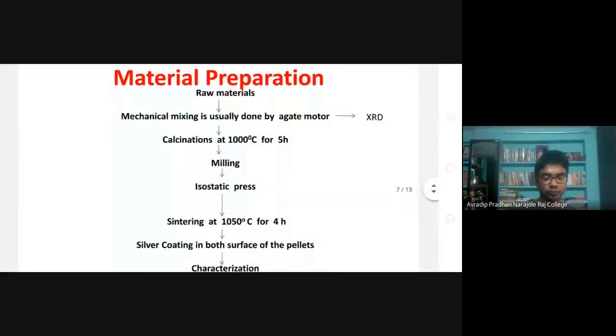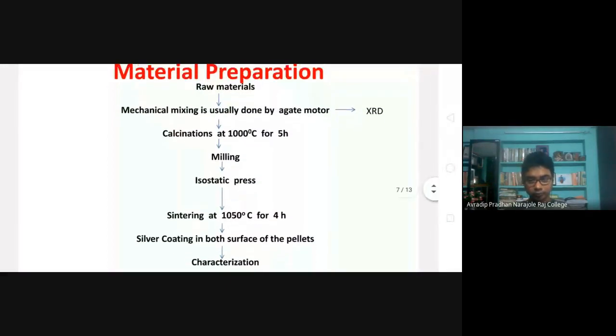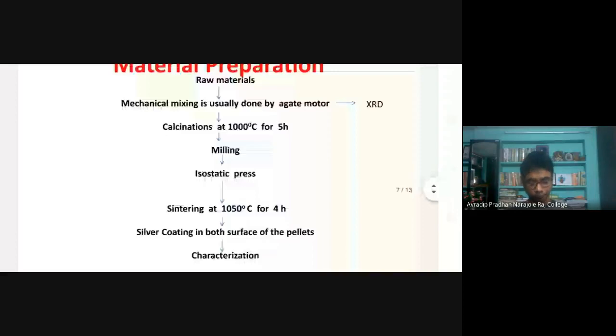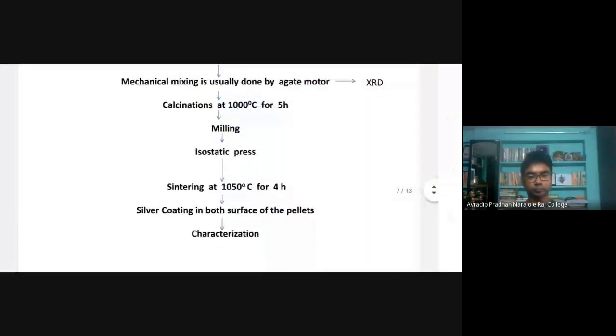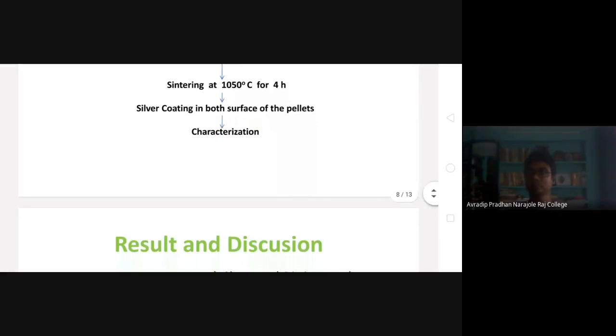This is the simple material preparation. We take the raw materials in the proper weight by ingredients, then mix them in the agate mortar with ethanol for 2 hours, and this is ready for XRD. After this mixing, calcination is done at 1000 degrees centigrade for 5 hours. Then it comes to milling, and the isostatic press in a hydraulic press to make the pellets. These pellets were sintered at 1050 degrees centigrade for 4 hours, and these pellets were silver coated very finely on both surfaces, and these silver coated pellets are ready for the characterizations.